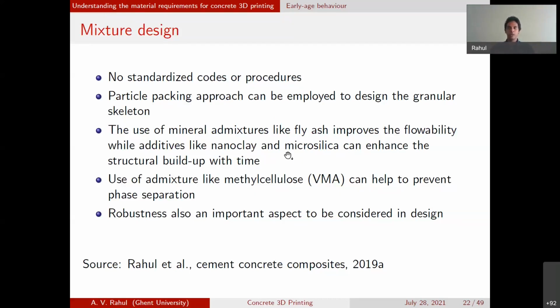For example, adding microsilica can really allow for a very fast evolution of compressive strength and elastic modulus because of its reduction in setting time. So this means that if you use this kind of admixture, you can have a much faster printing rate as compared to when you don't use microsilica. So the choice of mineral admixture also links with the type of print process that you want to have. And as I said, if phase separation is a problem, especially if you're using a piston-based system, as we discussed earlier, the use of methyl cellulose can be a good approach. Robustness is also a key element that we need to keep in mind.